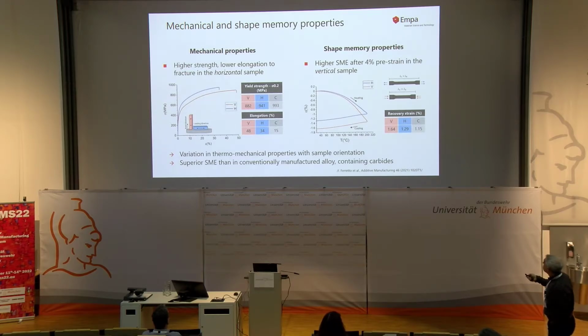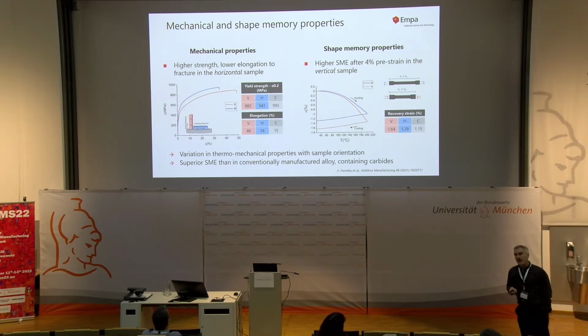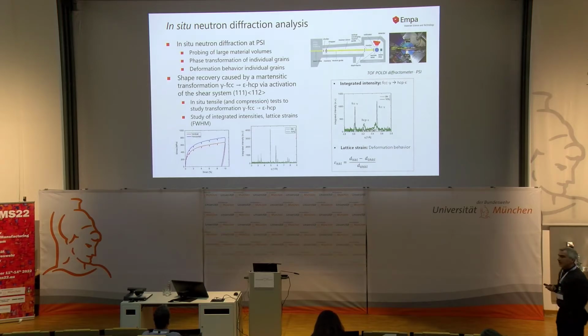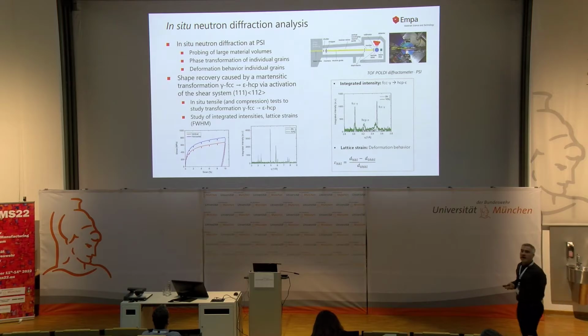If we look into the shape memory properties, the vertical samples exhibit a better shape memory effect than the horizontal samples. Here C means this is conventionally manufactured, hot-rolled material, so this rebar material, and we could see that we exceed the properties of the conventionally manufactured material. So why is that? Of course, it's the texture. That's the standard answer that you get on that. But now what does that mean?